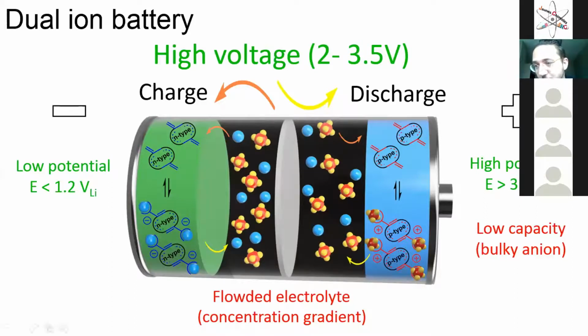So here all the potentials are higher than 3 volt. And we can use anode materials that have lower potential. And here you can maximize, you remember, the voltage is the difference between the cathode potential and the anode potential. But the challenge is these cathode materials store bulky anions, so you need to consider the molecular weight of this anion, and then the capacity will drop. And most of them don't provide a much higher capacity.